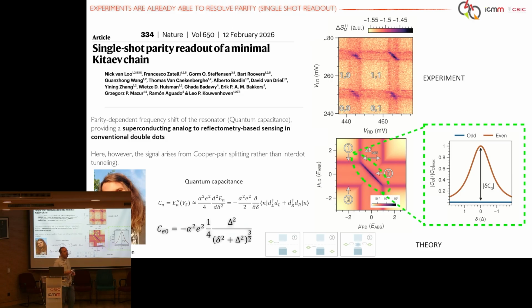So, coming back to Luis' comment, he's a theory equal contributor to a highly advanced experimental paper, which I think is important in this kind of collaboration. Anyway, you are able to read out this kind of signals. This is how the microwave signal changes a bit by the presence of your quantum dot, and you see these off-diagonal lines. You do a microwave experiment, you measure your LC resonator, and you see these tiny off-diagonals in the data that you can actually reconstruct by theory. This is theory from Gorm, where we understand very nicely these off-diagonal lines.